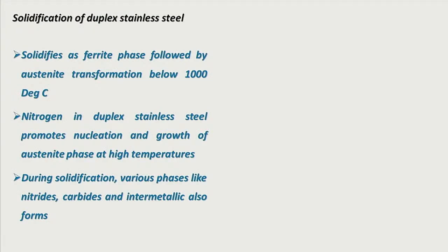The solidification of duplex stainless steel is entirely different from all the other steel materials, including carbon steel, austenitic stainless steel and ferritic stainless steel, because in this the solidification starts with ferrite phase followed by austenite transformation below 1000 degrees Celsius. The advantage of duplex stainless steel is the addition of nitrogen. This addition of nitrogen promotes the nucleation and growth of austenite phase in the material at high temperature, and during solidification various phases form, unlike austenitic and ferritic stainless steels, like nitrides, carbides and a lot of intermetallics. So this is the solidification pattern of a normal stainless steel based on the chromium and nickel equivalent, as we know.